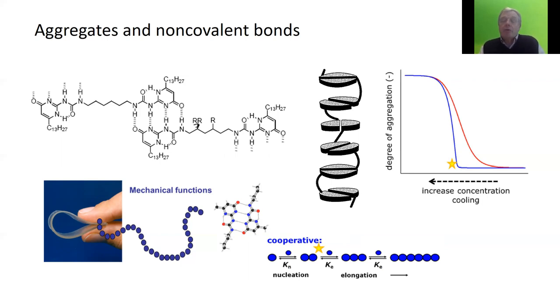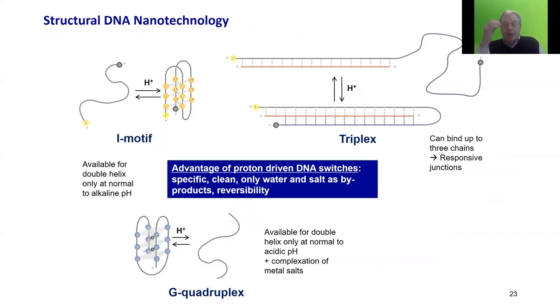And the improvement comes from the cooperativity of this type of effect. When the first disc is formed, it helps the second disc to form on top, and this helps the third disc to form on top. And you see here what would be if the disc would form independently from each other. You would have this type of smooth transition from bonded to non-bonded. And if they are stacking like this, you have the transition like it is shown here, with a critical concentration and a strong cooperative effect, which makes the material even stronger in there.